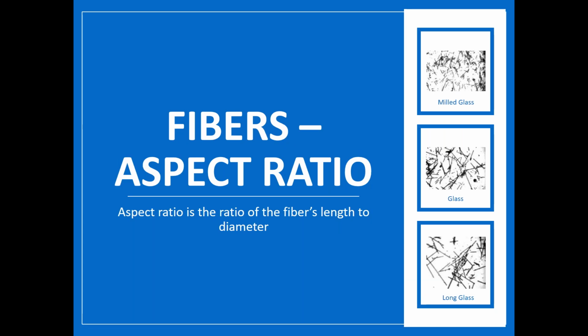So aspect ratio, I brought it up quickly. Essentially, if you hear this term or someone says it when they're talking about glass fiber, it has to do with the fiber's length to its diameter. Glass fibers are cylindrical in shape, and because of that, that's what aligns in the flow when you're molding it. That's also what gives it its strength, because it will line up in that direction. And then these quick pictures are a little blurry, but they do give you an idea. You can see the milled glass is a little bit shorter than your standard glass compared to your long glass fiber. So again, aspect ratio is what causes the anisotropic shrink, but also the directional performance that you get out of the material. I just wanted to bring that up in case you hear that term and were curious what it meant.